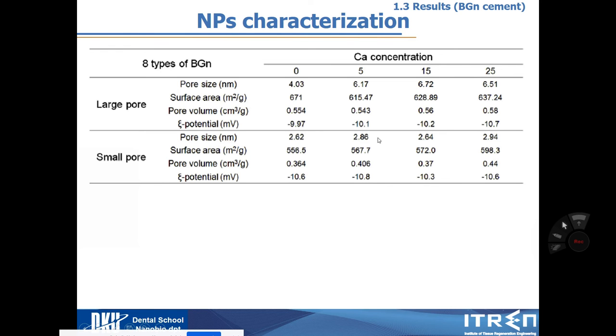They have a little bit of difference between small and large pore. When you look at the pore size, 4 or 6 is large, 2 or 3 is small. But the surface area and pore volume are even larger in the large pore compared to the small pore. And then I chose this 15%